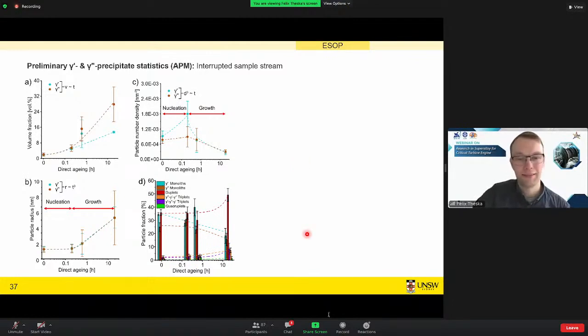Okay, so maybe you missed something: in this figure, after 10 hours, the volume fraction of the gamma double prime is much larger. So if you prolong this for long hours, let's say 1000, do you think that gamma double prime will have more volume fraction than this, or is there some equilibrium state in which there's no change between the gamma prime and gamma double prime volume fraction? Up to 650 degrees, it should be stable. But for very long-term exposure, we haven't done any experiments. It might be that some TCP or Laves phases form then. That has been reported in some long-term exposure studies. But yes, that would be something to explore for sure. Okay, I think it's enough. Thank you.